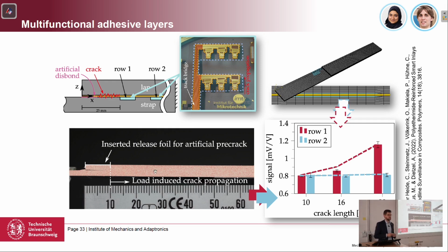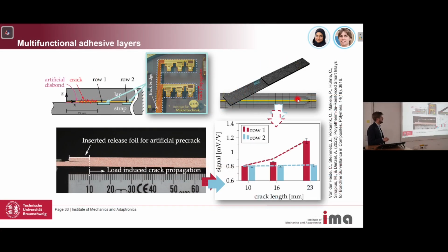And the idea for sensing is now that we have these two rows, and if the crack reaches the first row of multifunctional elements, the strain signal rises, and this one keeps at a low level. So the difference between these rows will tell us that a crack is growing inside the structure. And we also virtually tested it with finite element simulations and had quite good agreement between the sensor signals from the experimental test and also from the simulation.